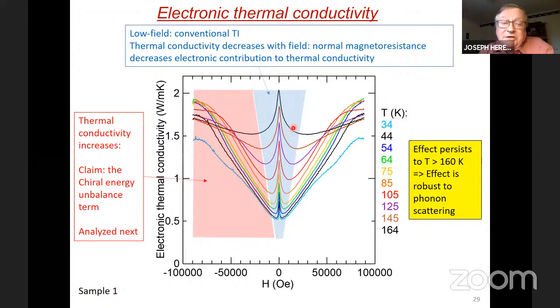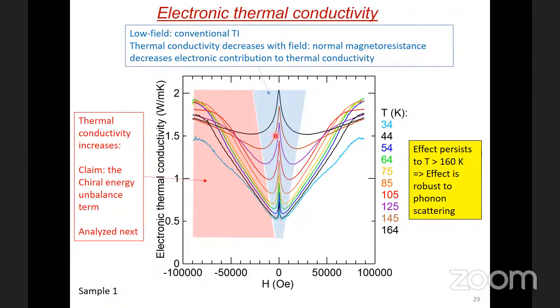The other thing you note, let's go over this here. So what we will claim now is happening here is that at low field, like here, we are really in the topological insulator mode. We have not reached the extreme quantum limit yet. We have conventional magnetoresistance, positive magnetoresistance, and we have a decrease in thermal conductance because of that. But when we get to the ultra quantum regime, and of course there's some thermal smearing, which explains why these lines smear out a little.